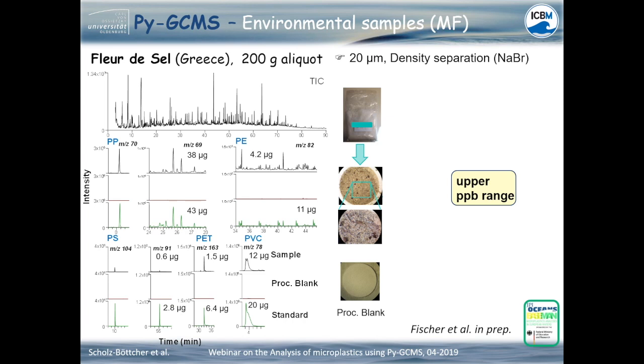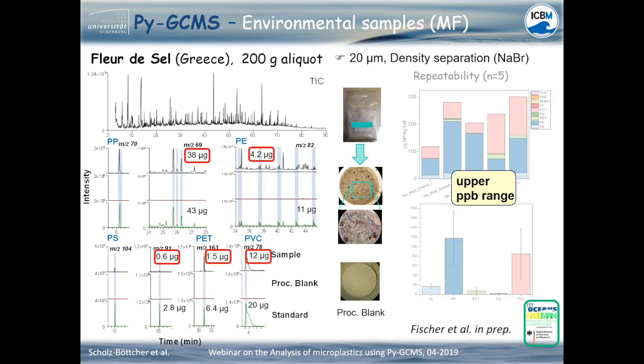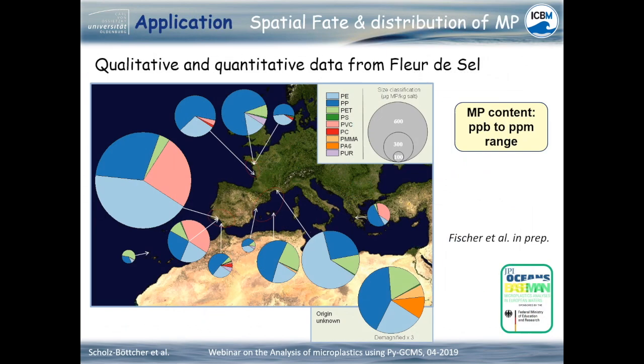The analysis was performed 5 times, and the samples were directly analyzed without further homogenization. This was done to avoid a particle fractionation in the sample and is clearly shown here in the variability of the data. This slide gives an impression of the spatial fate and distribution of microplastics generated from data of the fleur de sel study. Without further stressing this figure, it shows the potential of the generated data for further discussion regarding sources and concentrations of microplastic in the environment.